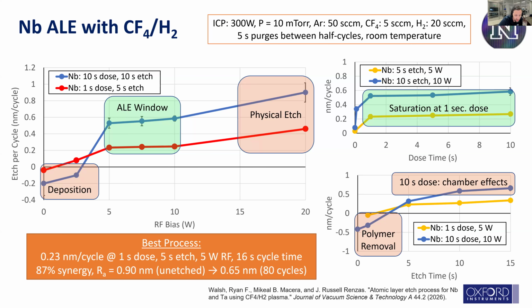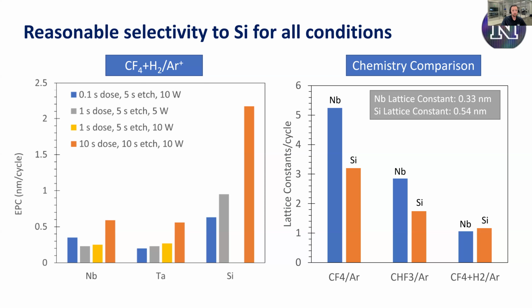We also looked at the selectivity. As I mentioned before, we cared a lot about that. And we even compared what that selectivity looked like for different chemistries. We thought the selectivity was pretty reasonable, actually. It's important to note the silicon lattice constant is quite a bit bigger, so I tend to think in terms of multiples of the lattice constant. On the right, you can see when we used our CF4 hydrogen process, we were very close to 1 lattice constant per cycle for both materials. So really, the silicon is etching a little bit faster, but relative to the lattice constant, it's pretty comparable. We're really happy with that, and it did outperform the other chemistries that we tried ALE with.